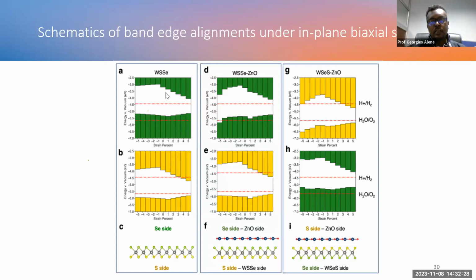And what we have noticed is that when we apply tensile strain, the conduction band minimum is reduced in its energy value. Then for the heterostructure, we have also tried to investigate the effect of strain and without strain on photocatalytic activity. For the WSSe zinc oxide heterostructure, we found that at zero strain, that means without any strain, it is good for hydrogen evolution reaction, but not good for oxygen evolution reaction. When we see it on the S side for the heterostructure, we have noticed that it has more or less similar property to the monolayer WSSe.